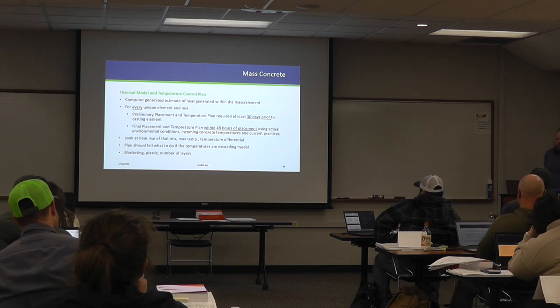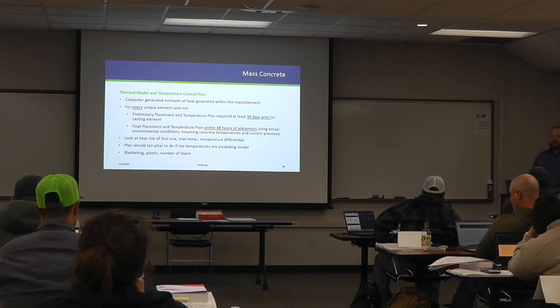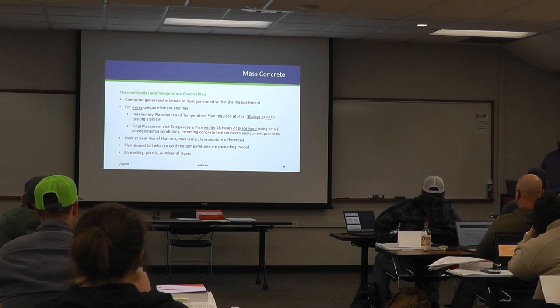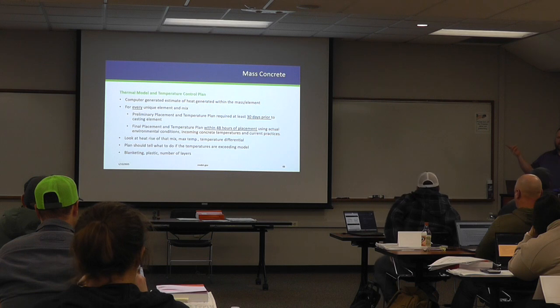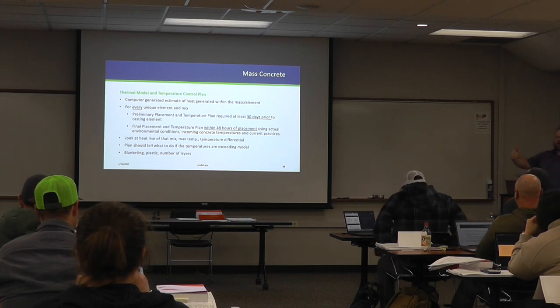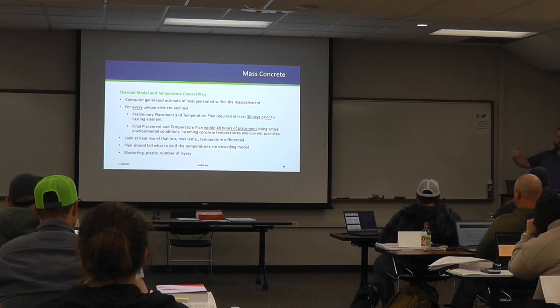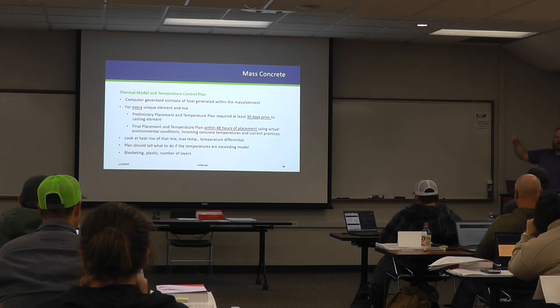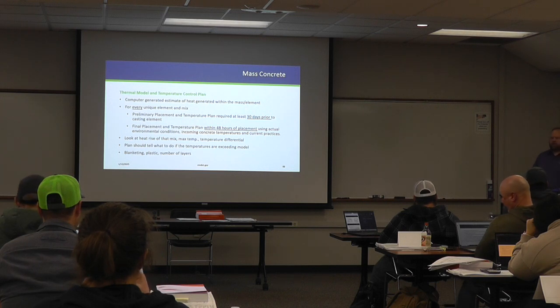Well, at that point, if you place the concrete and the max temperature is exceeding that, unless you have cooling tubes in that element to be able to pump water through, you're pretty much at the whim of the concrete. And we've got a table in the spec that lays out monetary deductions based on that max peak temperature. It gets pretty quickly to remove and replace. I think it's like $1 or $2 per yard for 160 to 165, and I think it bumps up to like 20, then 50, then remove and replace.